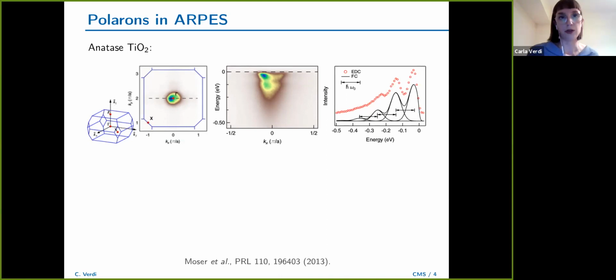So to do ARPES, you dope the material. So there will be a pocket of electrons near the bottom of the conduction band shown here. This is the gamma point, the center of the Brillouin zone. When you look at the ARPES intensity map, you see something quite different to what you would normally expect to see. So there is a parabolic band here. Of course, there is a lot of broadening, but again, we're looking at energy scales of just a few hundred milli-electron volts. So there is a parabolic band, and this is followed by another parabolic band and some more tail.